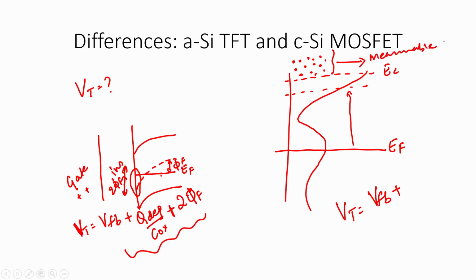So, that is the definition of threshold voltage, which is a very vague definition, because it depends upon your density of states profile. If the density of state distribution is very large, you need to trap a lot more carriers before the Fermi level can climb to that point, and therefore, your threshold voltage is going to be much larger. Okay. So, let us say that this is the location of the Fermi level when there is significant carrier population in the extended states.